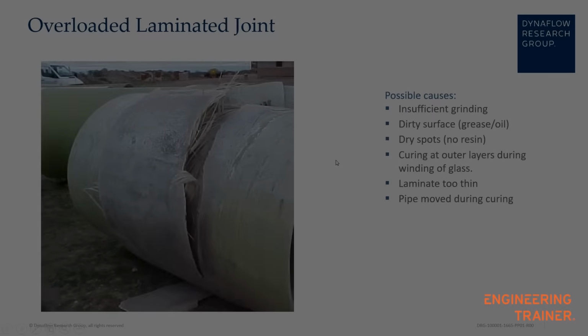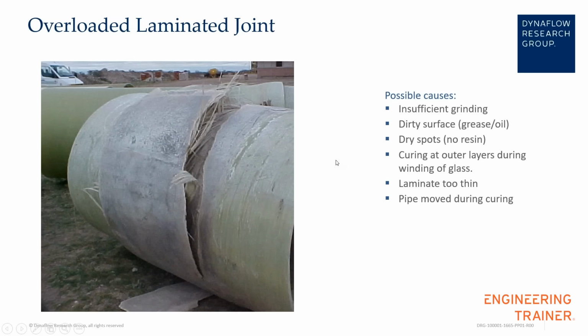installation errors. Here we see an example of a failure of a laminated joint. Possible causes are partly the same as for the adhesive joint, but also some different causes. So again, it is important for this type of joint that you do sufficient grinding. Also, you don't want contamination of grease or oil or water. But what is also something that you don't want with laminated joints is dry spots.